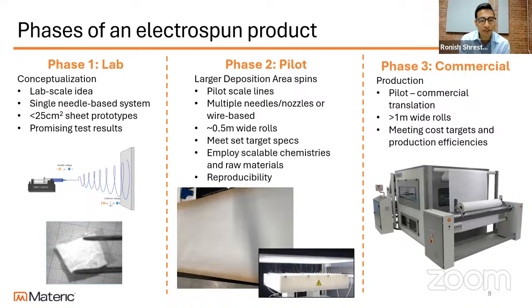Once we're translating from the lab scale to the pilot scale, meeting the target specs that people were seeing on the lab scale is also very important. The process is slightly different. It's a continuous process, not a batch one. So we might end up with a lot of differences, and optimizations have to be done to meet those target specs. And the most important one is reproducibility, just reproducing that at different conditions, on different days. And so that all the procedures that we develop for phase 2, for the pilot scale, can be transferred to phase 3, the commercial scale, which is the commercial production of the material, usually done in greater than 1 meter wide rolls.